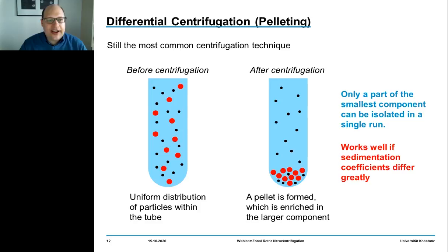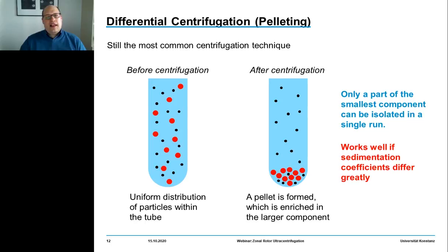Differential centrifugation works reasonably well if the sedimentation coefficients of the particle populations to be separated differ by at least one order of magnitude.